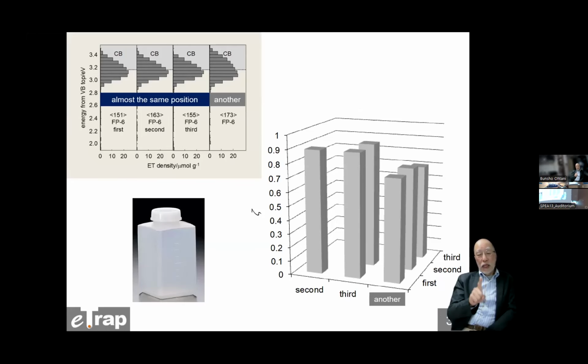So that means 2 points. One is that this measurement is very, very sensitive, especially to surface structure. And the second point is, even in the same bottle, the sample is a bit different, probably in the surface structure or the surface water, which might give such a difference. So therefore, it is necessary to think that even in the same bottle, the content is a bit heterogeneous.